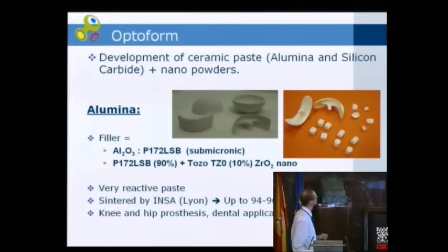We'll start with the alumina paste. Two different pastes have been made. One paste is made of submicronic alumina, and the second paste is composed of 90% submicronic alumina with an addition of 10% nanometric zirconium oxide. This paste is very reactive because these two components, alumina and zirconium oxide, are transparent to UV. Thus there is absolutely no screening effect in this case. The parts were sintered by INSA in Lyon, and we reached a final density of 94 to 96%. And we have some examples here of the parts that have been made. So we have knee or hip prostheses or dental prostheses made for Nobel Biocare.